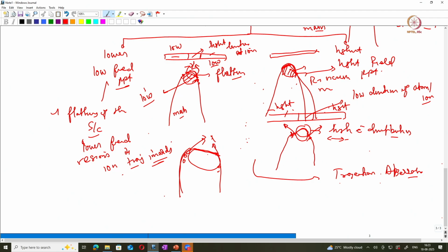And due to that reflection, usually the trajectories will get deflected away from the sharp surface of the precipitate. Okay, and this results in a decrease in the density of atoms which are hitting just ahead of the precipitate. So this is the second type of aberration, which is called a trajectory aberration. So first was the roll up, the second one is the trajectory aberrations,